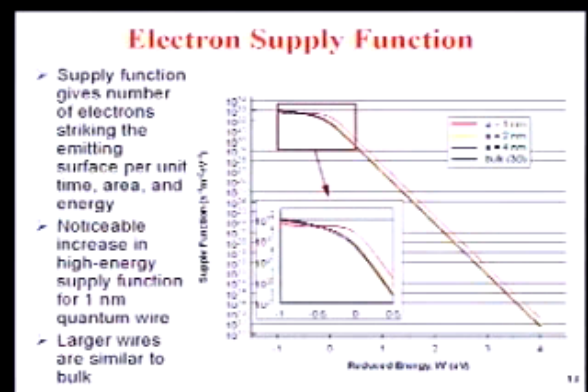The important thing here, it's a little bit technical, but not too bad, I hope, is the electron supply function. This is the number of electrons that hit the emitting surface per unit time, per unit area, per unit energy. I have a fairly large energy scale here because, even though the supply function is much lower for high energies, we still are interested up here because the work function may be that high. In the inset, the different curves correspond to different sizes of quantum wires, 1, 2, and 4 nanometers, and also the three-dimensional result for a bulk material.